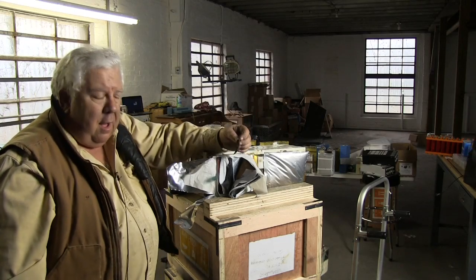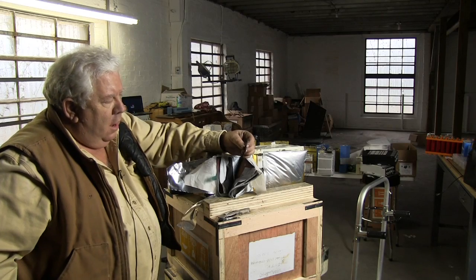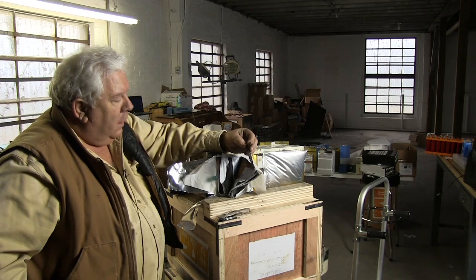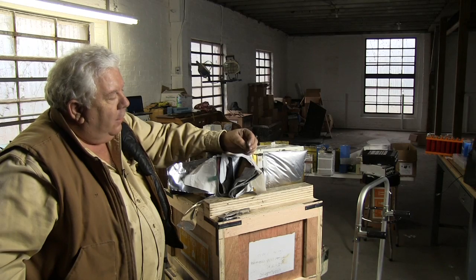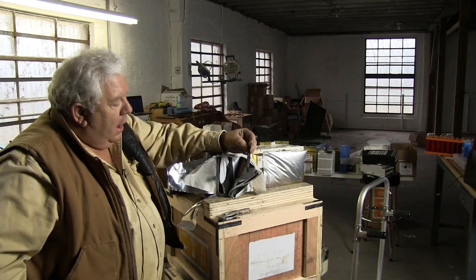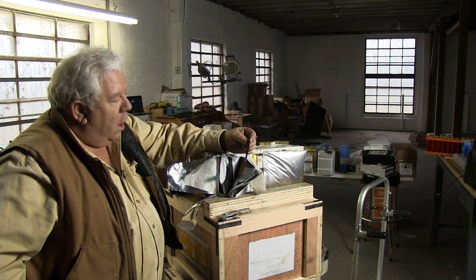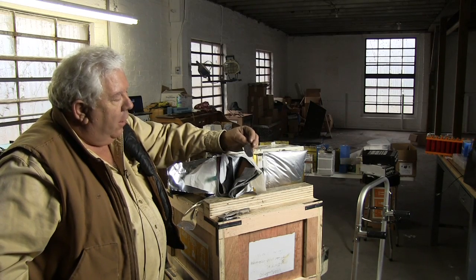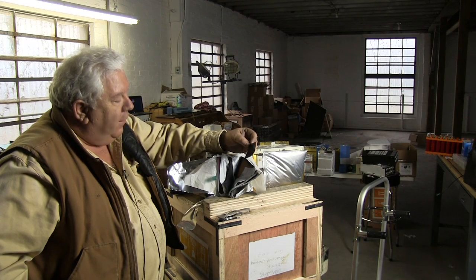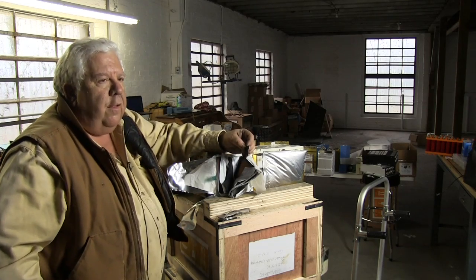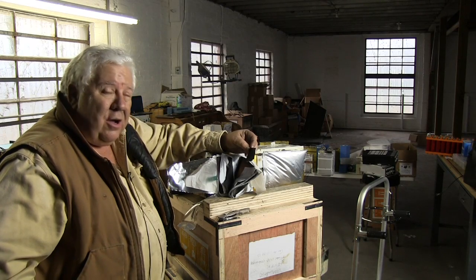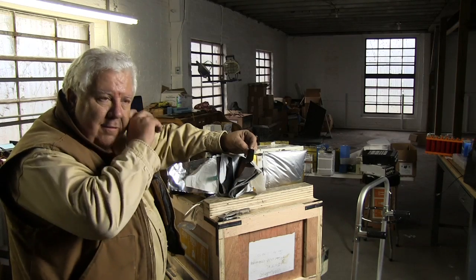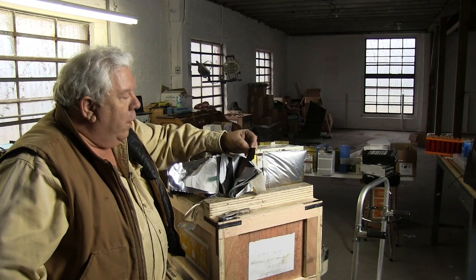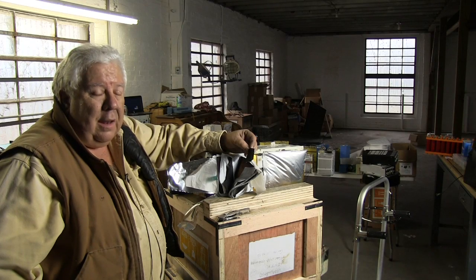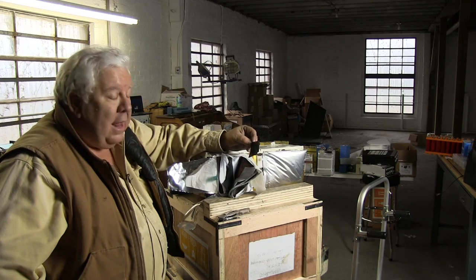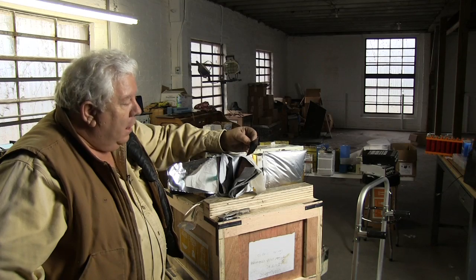Now this is kind of interesting. It goes to the heart of a patent dispute. The professor at MIT who's claiming these cells don't have anything to do with the Phostech patent, Hydro-Quebec, and the University of Texas at Austin. Professor John Bannister Goodenough and his team there had purportedly set up the lithium iron phosphate cell. One of the issues that they had in doing that was that lithium iron phosphate actually does not conduct. Now, it conducts ions just fine. They can tunnel into this porous lattice and intercalate with the iron phosphate just fine. But electrons from the anode or the cathode material, the aluminum, cannot penetrate the iron phosphate.